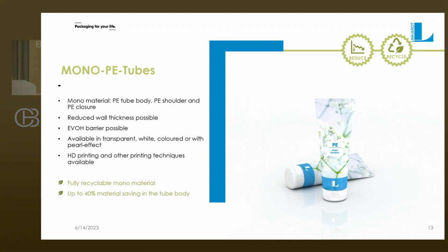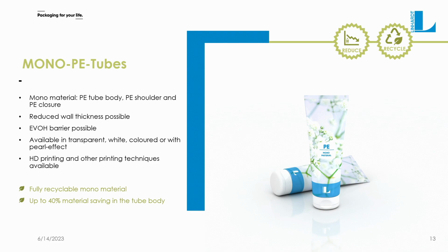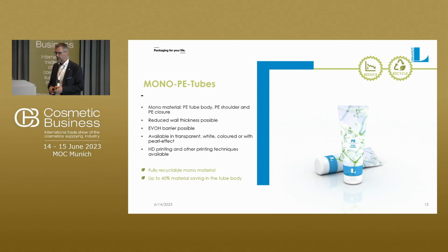So mono-PE tubes. This is a topic of recyclability because in the past, a PE tube had a PP lid, PP closure. Recently, we've started offering PE tubes with PE closures. We can do that. So for any diameter, we have a portfolio of caps and closures, also flip tops that will actually stand all tensile tests in PE, also in combination with the reduced wall thickness with the EVOH barrier.